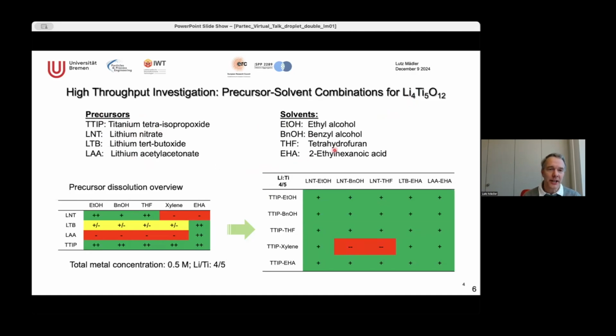And then you need some kind of solvent. And again, remember, that solvent should be combustible. So all the energy, or most of the energy in that process that drives the process, comes from the liquid itself. So the task here is to put some of those metals into a combustible liquid. And what we do is we use nitrates, but most of the time also we use metal organics, and we try to mix them together. And that's not always very successful.